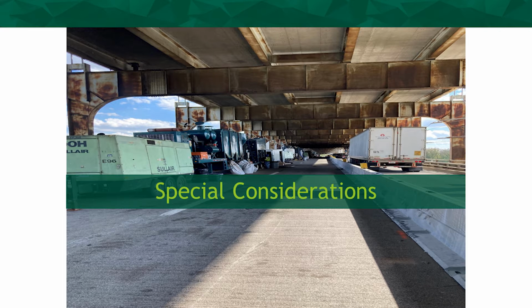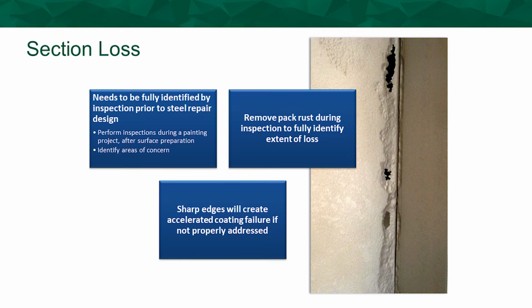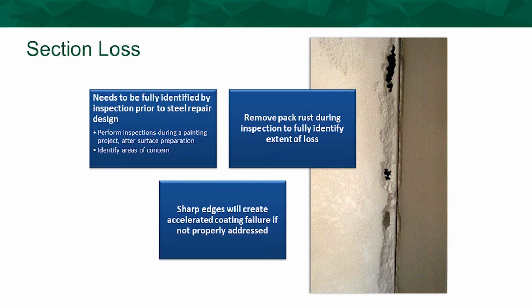Other special considerations, section loss. You want to make sure you address those areas before you paint the structure. You have sharp edges. Paint will flow away from edges, corners, rivet heads, and all that. So you want to make sure that you address section loss before you paint a structure. And again, as I just stated, sharp edges will create accelerated coating failure if not addressed properly. So those areas you want to stripe coat. And typically, stripe coating is done during the primer and intermediate application.